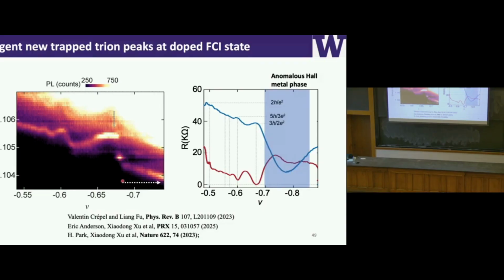And then as I keep doping the system, we'll enter into this anomalous Hall metal phase, right? Then you can see there's another change of the energy of the state, and the anomalous trion appears with a continuous dependence on the doping. So this bright feature showed up at the doped FCI state, right? I call it a fractional trion or anyon-trion. And I'll show you more evidence why we say that.